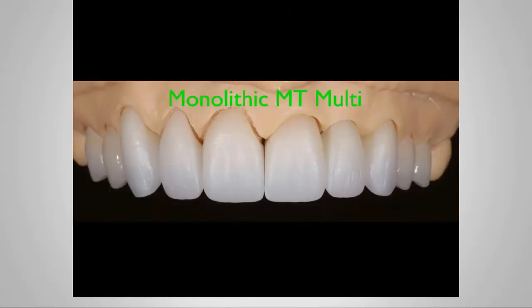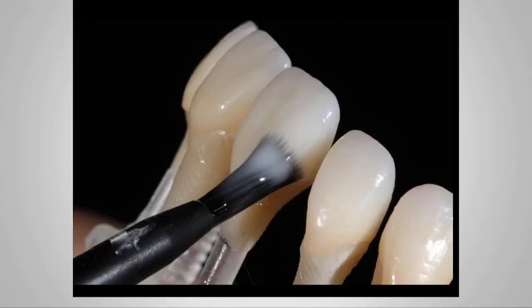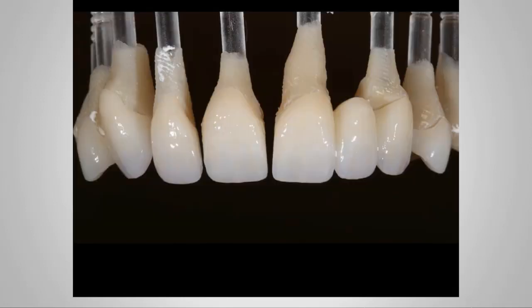Matt also decided we were going to do a couple extra crowns. So we're going to also see what it looks like on try-in if we did the monolithic MT multi on all 6 anteriors. So he went ahead and milled 3 more crowns on 6 through 8 just to give us a comparison. So this is going to be sort of a trial for us. You can see the posterior is still lithium disilicate. On those new 3, he's going to do the same as he did on the bridge, stain and glaze only.